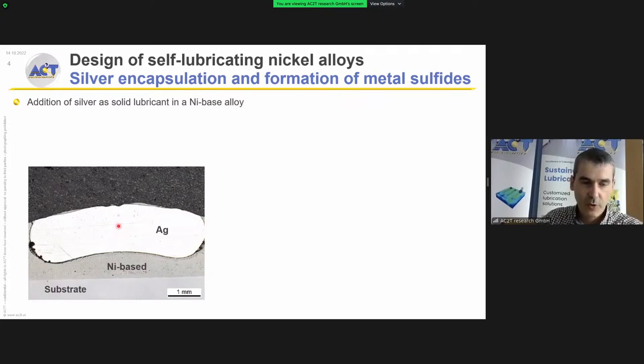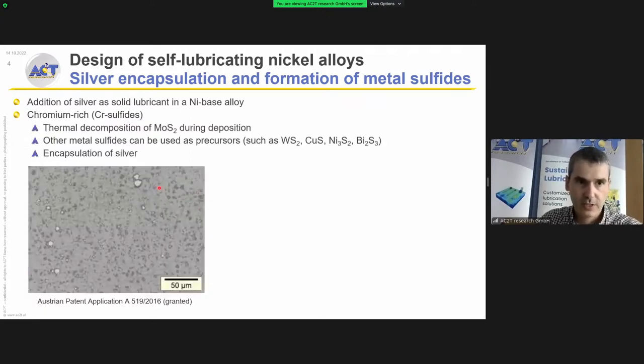So if we want to have something useful, we need to have this solid lubricant homogeneously scattered and distributed in the microstructure. And to do this, we need to have some diffusion barriers for the silver, and we can do it using, for example, sulfide compounds. So in our case, we use molybdenum disulfide that during the thermal deposition decomposes into chromium sulfide. This means that this process is not limited to molybdenum disulfide. Other sulfides can also be used as a precursor.